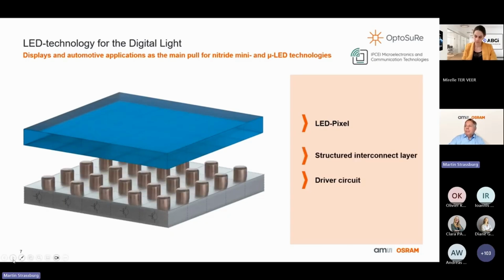That takes something like a structured interconnect layer. Here you can see just these metal bumps shown. It is of course much more complicated than a metal bump, this interconnect layer, but this has to be designed in a way that there's no overlap to neighboring pixels. For 40 micrometers, it's still a challenge. If you go even to smaller dimensions, it becomes more advanced.